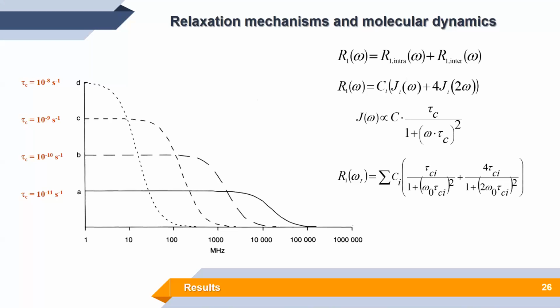When talking about analysis of these NMRD profiles, we need to think about the relaxation mechanisms and the molecular dynamics. One of the main contributions to the spin-lattice relaxation time is intermolecular and intramolecular spin-spin interactions modulated in time, for example, by translational displacement over distances greater than the size of the molecules that we study, or by reorientation of the spin system that we investigate.